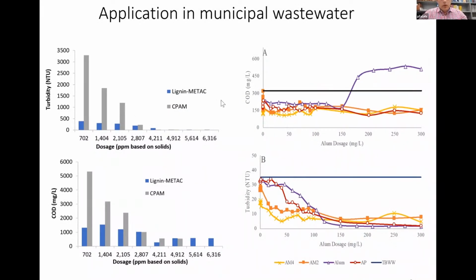Again, we compare our polymer with the material they use on a daily basis. And again, turbidity is an indicator of the cloudiness or the dirtiness of the wastewater. And you can see the lower the number, the better. So you can see that our material, or even COD, the chemical oxygen demand of the water, you can see that we got much better results than the one they are using.